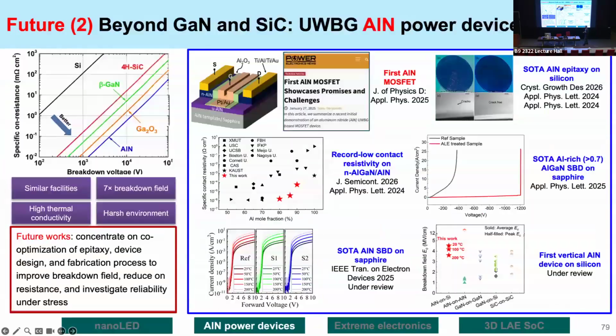Number 2 is that we want to move beyond gallium nitride and silicon carbide, right? If you look at the figure on the bottom left, this basically shows the Baliga figure of merit for different power semiconductors. Obviously, first of all, we have silicon, and now it's moving to silicon carbide and gallium nitride. And the ultimate power semiconductor here is aluminum nitride. It will have the largest possible figure of merit.